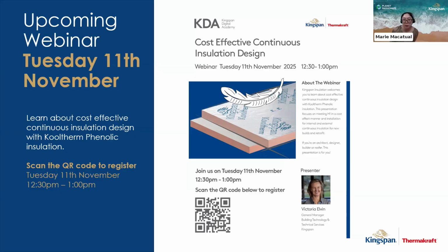Good. And what is suitable foam to fill gaps in PIR? As with our Kooltherm product, we would always say a non-solvent polyurethane expanding foam. We have a variety that people have worked with in the past, but commonly it is part of a proprietary system that will still be tested as part of their system to ensure that they have compatibility. There are some very detailed requirements about chemical interaction that are listed on our data sheets for PIR as to what chemicals cannot be used, but as a general rule, a non-solvent polyurethane expanding foam would be ideal to fill the gaps that you might see between insulation materials.